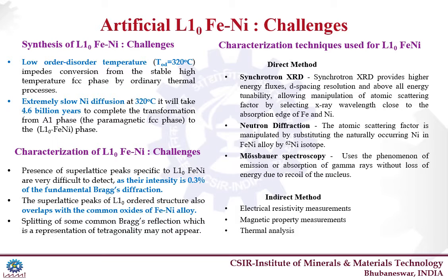Characterization of L10 FeNi is also difficult as it cannot be detected by simple XRD or electron diffraction. Synchrotron XRD and gamma ray absorption spectroscopy are generally used to detect L10 FeNi. Also, it can be indirectly detected by measuring small changes in thermal, electrical, and magnetic properties.